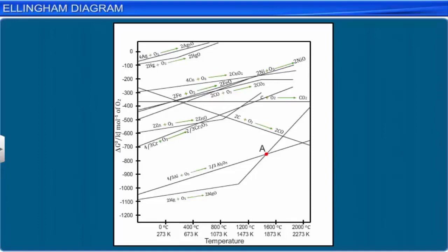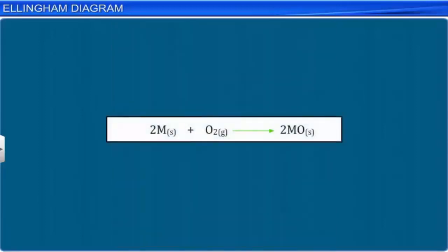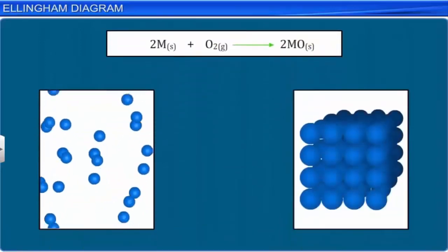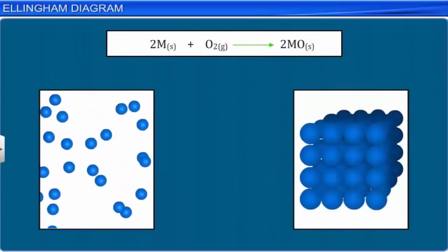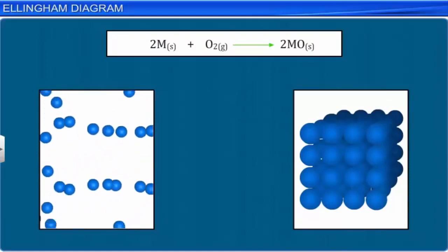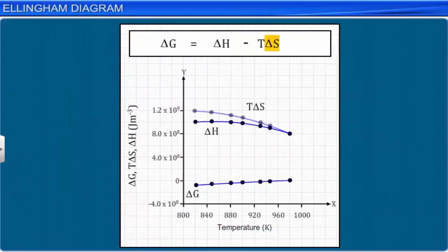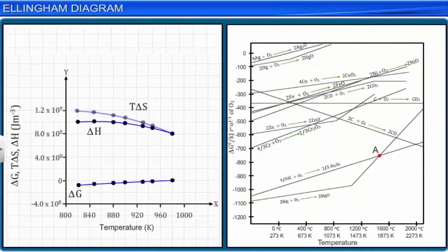The first feature is that the graphs for most metal-to-metal oxide reactions show a positive slope. Consider a reaction such as the formation of an oxide, 2M plus O2 gives rise to 2MO. In this reaction, the entropy or randomness decreases from left to right due to the consumption of gases. Hence, delta S becomes negative. Thus, if the temperature is raised, then T delta S becomes more negative. Since T delta S is subtracted in the equation, delta G becomes less negative. Thus, the free energy change increases with an increase in temperature, and hence, the plots show a positive slope.